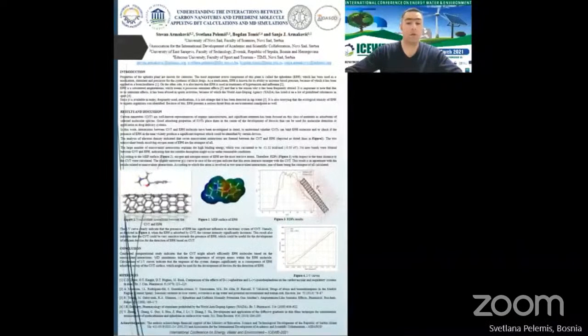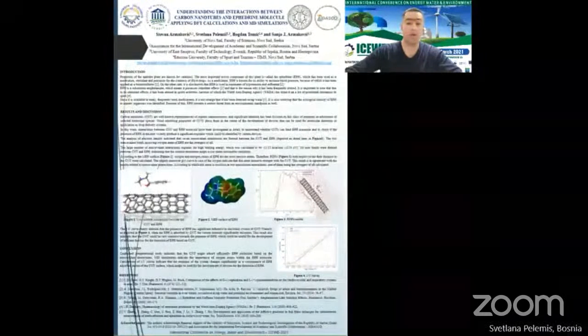The current voltage curve clearly indicates that the presence of ephedrine has significant influence to the electronic system of the carbon nanotube. Namely, as depicted in figure 4, when the ephedrine is absorbed by the carbon nanotube, the current intensity significantly increases. This result also indicates that the carbon nanotube could be very sensitive towards the presence of ephedrine molecule, which could be useful for the development of efficient devices for the detection of ephedrine based on carbon nanotube.